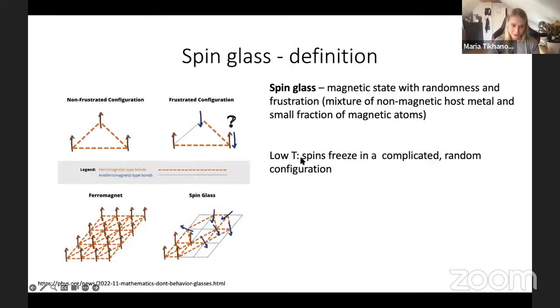All right, so let's first define the spin glass. Spin glass in condensed matter literature is defined as a magnetic state with randomness and frustration, which is essentially a mixture of a non-magnetic host metal and a small fraction of magnetic atoms. So you dope your non-magnetic host metal with magnetic ions, and essentially what you get at low enough temperature is that spins start freezing, and this freezing is happening in a very complicated random configuration. Imagine that at very small temperature, you can end up in a ferromagnet. But sometimes if you have your non-magnetic host metal with the magnetic atoms, then you end up in this very weird configuration. And that all happens because you have both frustration and disorder in your system.